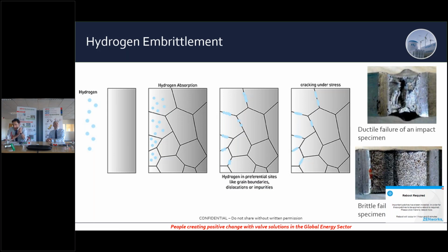So typically, valves are made to be operated in demanding circumstances, and as such are made from high performance exotic materials, duplex, super duplex, high nickel alloys as just a few examples. But these all can be susceptible to a condition known as hydrogen embrittlement. Now, hydrogen can absorb into a material structure. It can congregate at grain boundaries, as the image on your screen will show, and these can be either dislocations or even impurities. What happens when it congregates is it can result in a loss of ductility within the material, and doesn't necessarily affect the yield strength, but can, in worst cases, lead to catastrophic failure of a component.